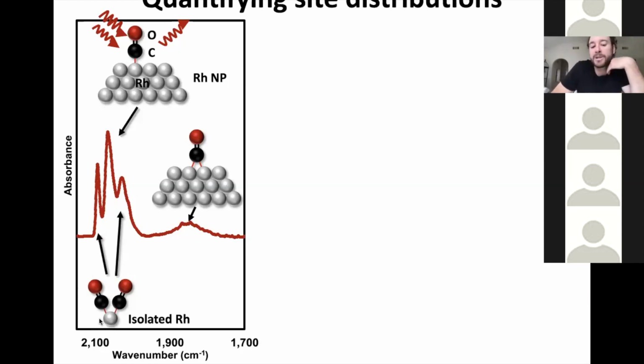However, if CO bonds to isolated rhodium species or single rhodium atoms, what you form is a dicarbonyl structure. On the other side of this, we should be making two bonds to the metal, so that we have essentially a square planar complex. And this dicarbonyl can stretch in two different ways: a symmetric stretch, which is this one here, or an asymmetric stretch of the dicarbonyl. So through this infrared spectroscopy, we can decompose what is exposed on the surface of a rhodium catalyst into sites on nanoparticles by these two bands and sites on single atoms by these two bands.